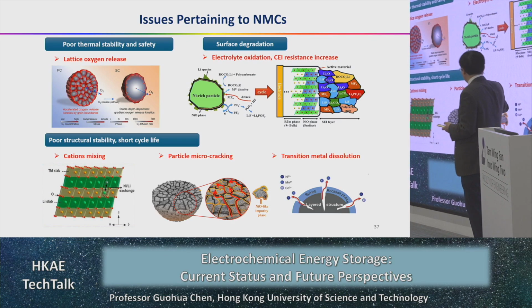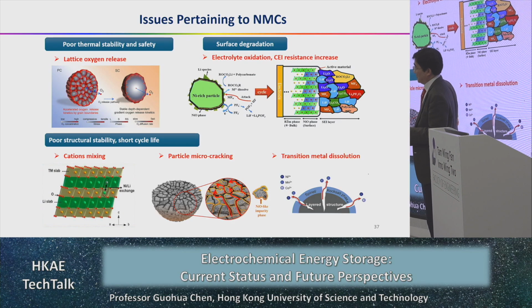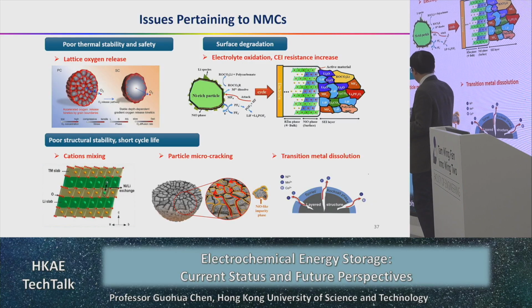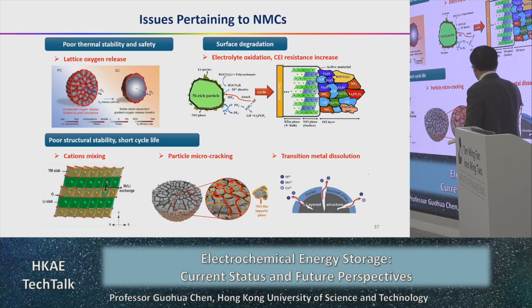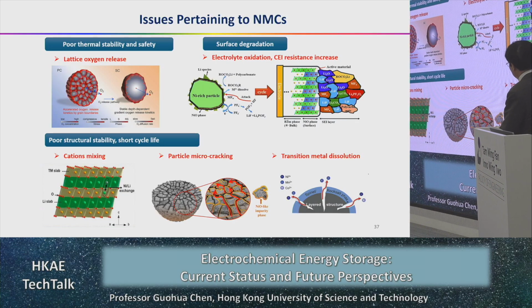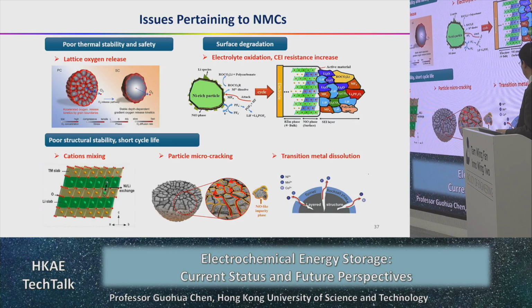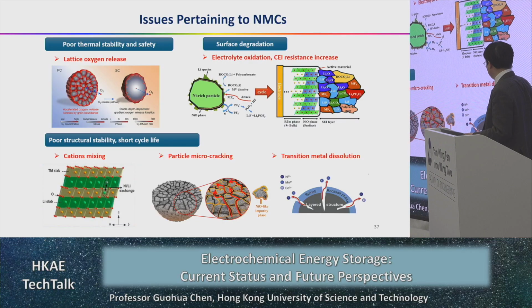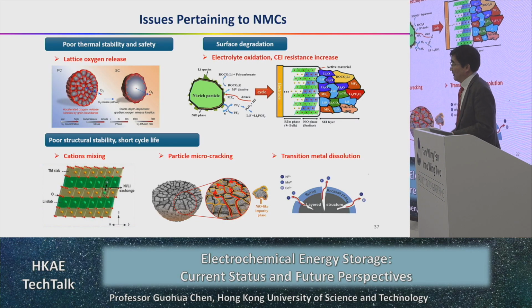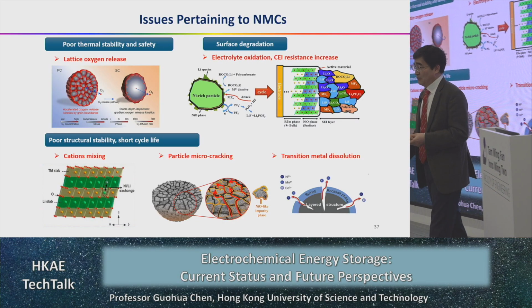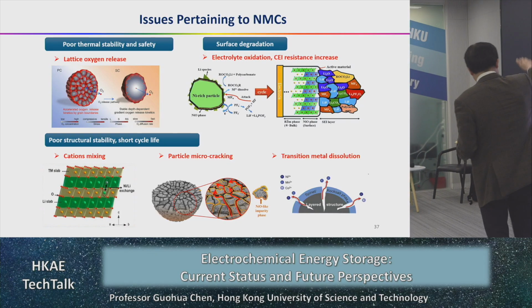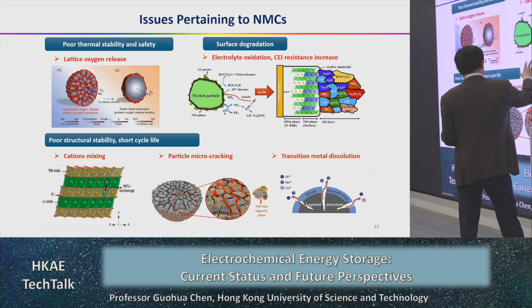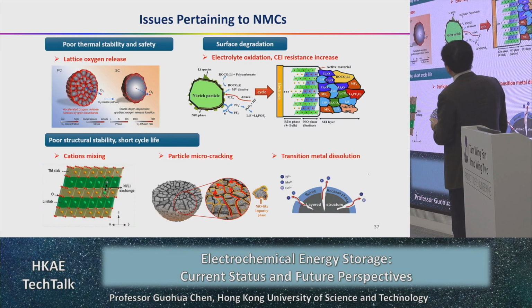After hundreds of cycles, you have micro cracking, so that the particle would get pulverized. And transition metal can also be dissolved into the electrolyte and cross over to the anode, and then the service life and safety of the battery will also be affected.